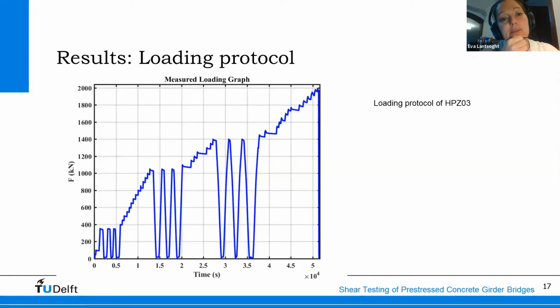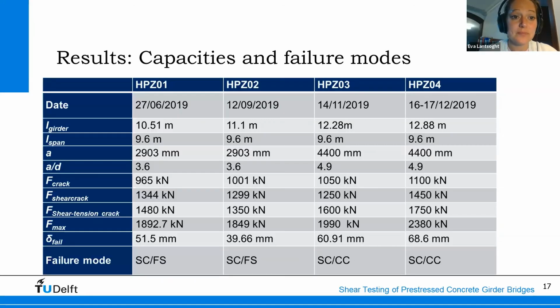In terms of loading, we used a loading protocol with loading to different levels and unloading, so that we could follow the opening and closing of cracks, and we could use this for determining the wave-based properties. Here's an overview of the results of the 4 experiments. You can see that they've been tested between June 2019 and December 2019 with the properties of the geometry.